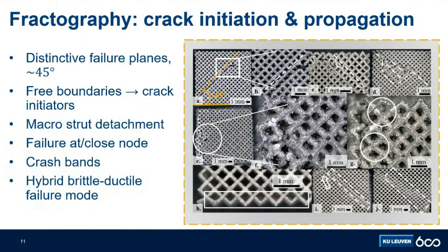For the fractography study, consistent with the theory, we can observe distinctive failure planes at around 45 degrees, both for the as-built, which are on top, and for the hardization treated. The free boundaries of the lattice structure, which is a cube, act as crack initiators. As you can see here, we have more extensive damage on the outside, and then the cracks progressively make their way inside the structure. We observe macro strut detachment, and the failure happens at the nodes or close to the nodes.